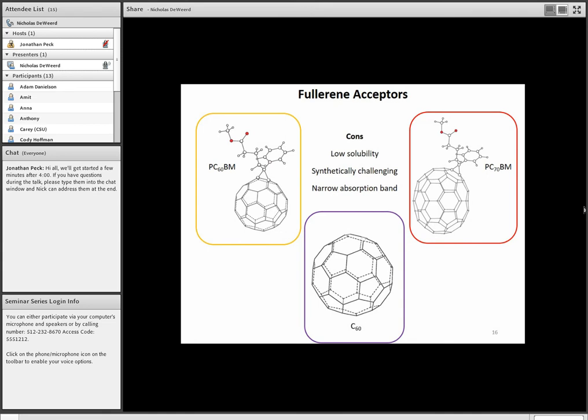On the con side, they do suffer from lower solubilities. They are synthetically challenging; I work on fullerenes and fullerene syntheses, and in general, fullerenes are more difficult to work with than their small molecule counterparts. Also, their absorption band is narrow, only between roughly 300 nanometers and 425 or 450 if you have a para addition. When you're trying to saturate the number of photons from the incident light of the solar spectrum, you want as broad an absorption band as possible. There's no reason that the acceptor can't contribute to the number of photons being absorbed by the device.